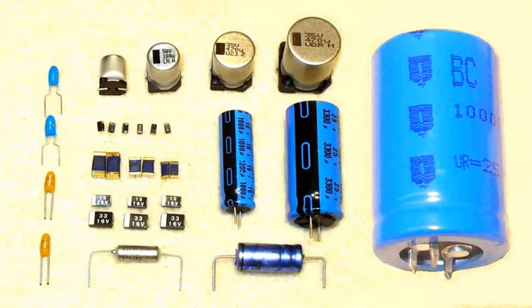For tantalum capacitors a DC bias voltage of 1.1 to 1.5 volts for types with a rated voltage of 2.5 volts, or 2.1 to 2.5 volts for types with a rated voltage of greater than 2.5 volts, may be applied during the measurement to avoid reverse voltage. The capacitance value measured at the frequency of 1 kHz is about 10% less than the 100/120 Hz value. Therefore, the capacitance values of electrolytic capacitors are not directly comparable and differ from those of film capacitors or ceramic capacitors, whose capacitance is measured at 1 kHz or higher.